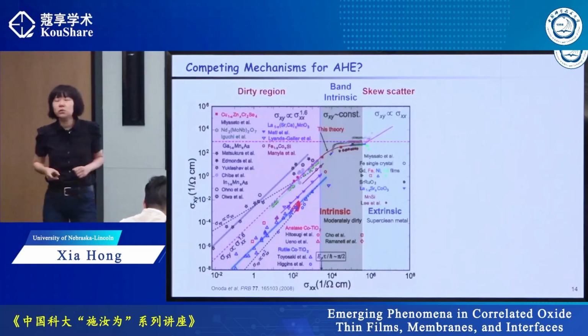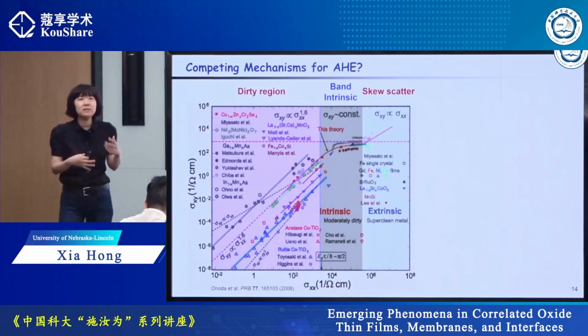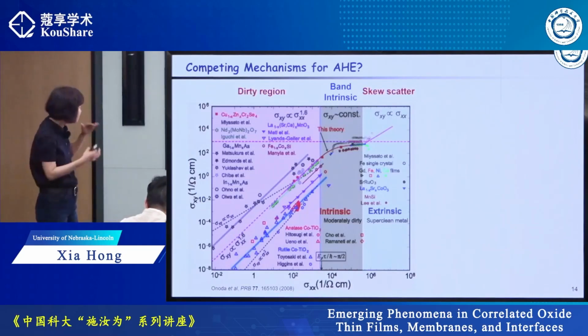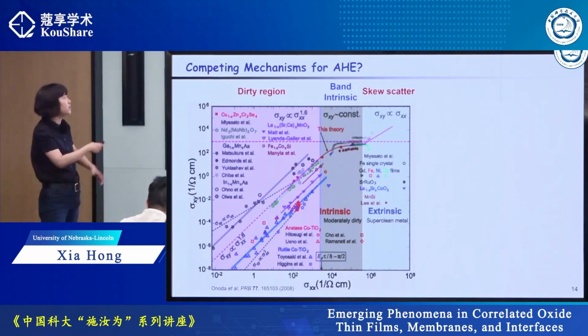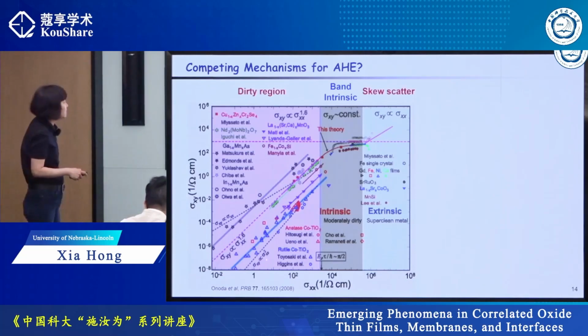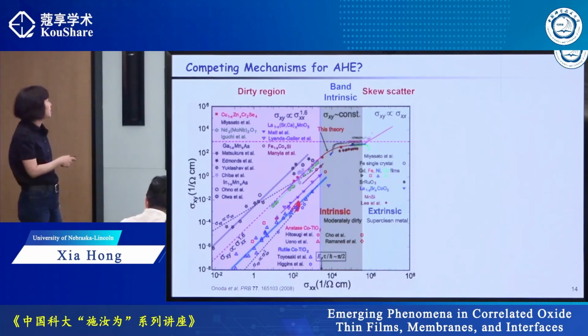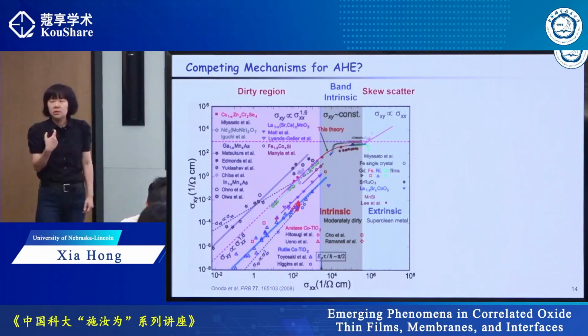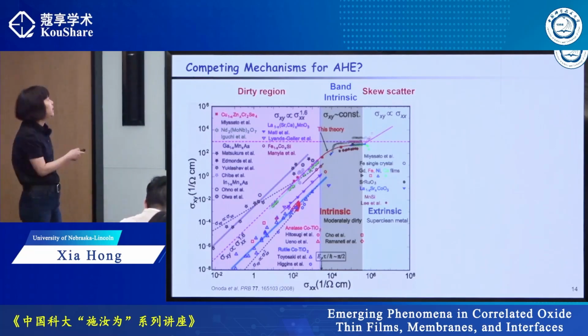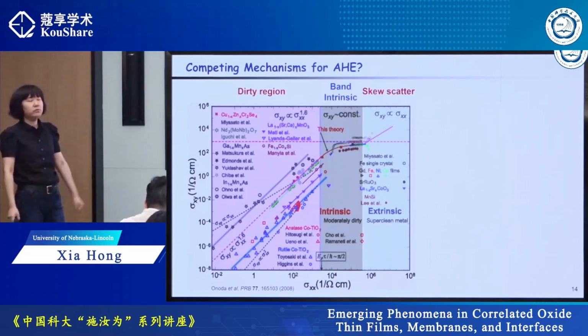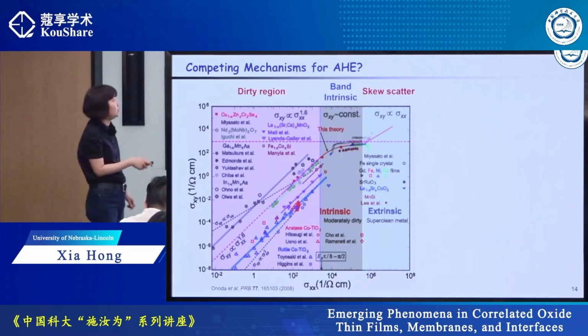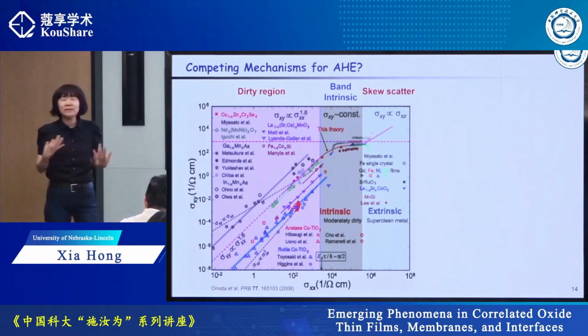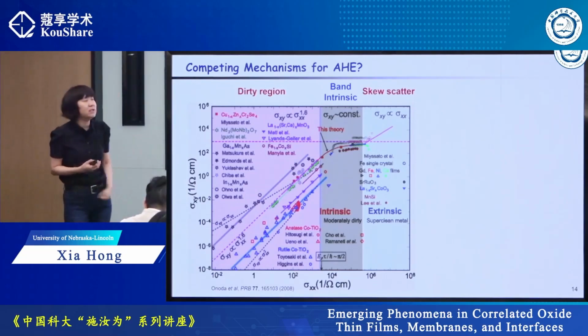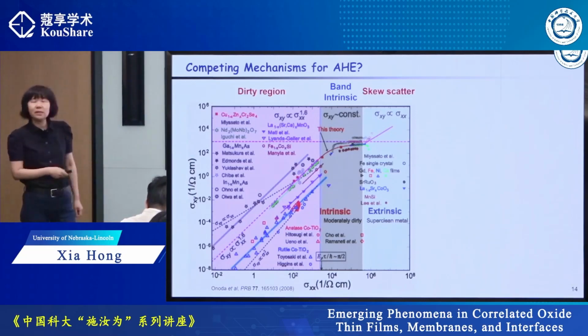So now let's look at what can change anomalous Hall. So this is basically counting the Berry phase effect below the Fermi level for those magnetic oxides. And people have tried to summarize anomalous Hall observed in different materials. They find that if you scale sigma xx with sigma xy, it can be divided into 3 regions. If you have a super clean sample, then it's determined by skew scattering. So this is the extrinsic mechanism. And sigma xy should scale linearly with the sigma xx.